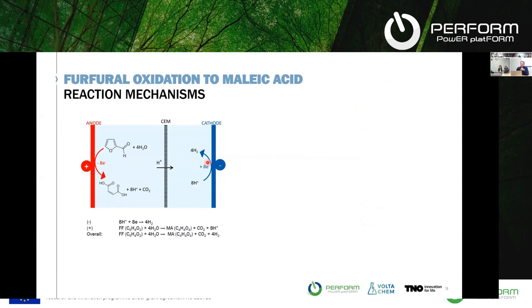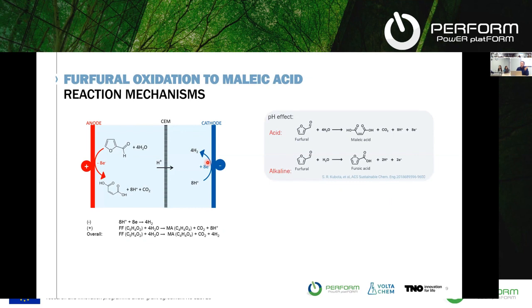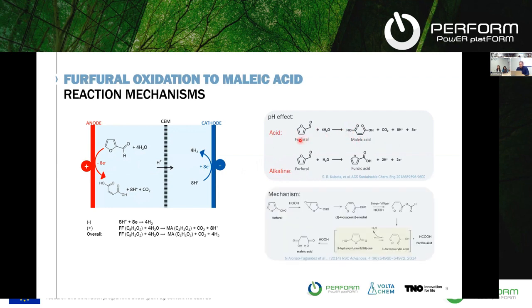Once you know something about your catalyst, you also typically would like to investigate a bit about the mechanism of your reaction, because maybe the mechanism, and so the product that you make, is influenced by the actual electrolyte properties. In this case, if you look at the effect of pH, if you carry out this oxidation from furfural on a catalyst in acidic conditions, you do get maleic acid as a product. However, when you do it in alkaline conditions, you get something different that might be desirable or not, but it's not the product that we are targeting. So in this case, we did settle for an acidic electrolyte, because maleic acid is the product that we wanted.